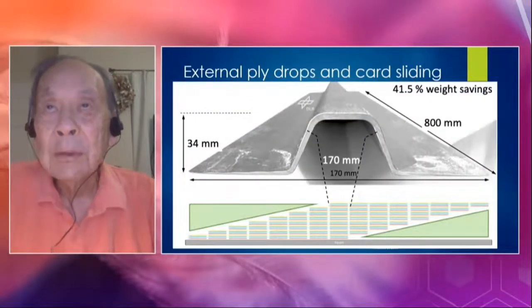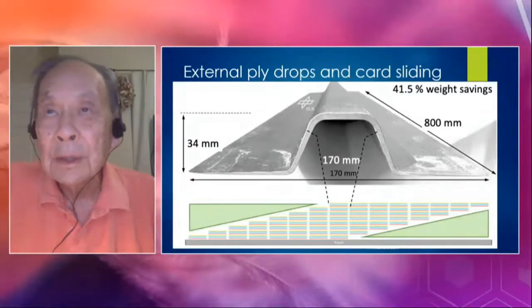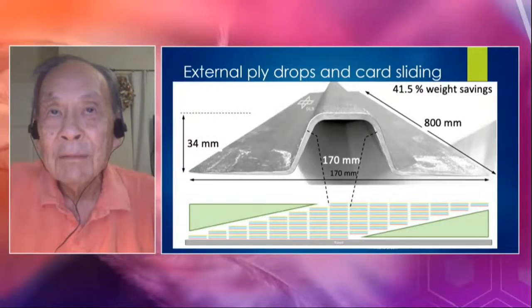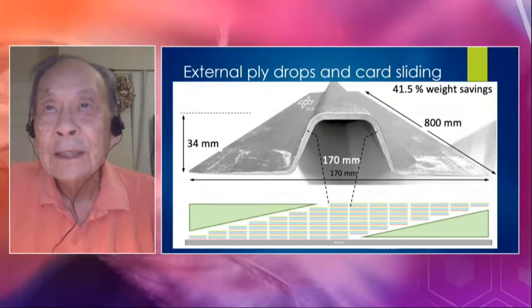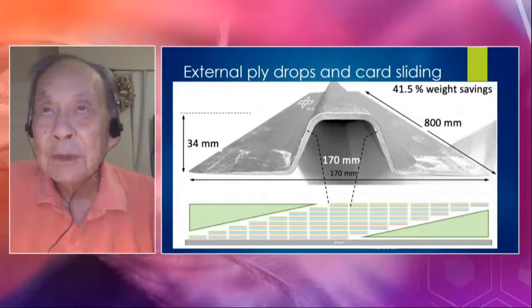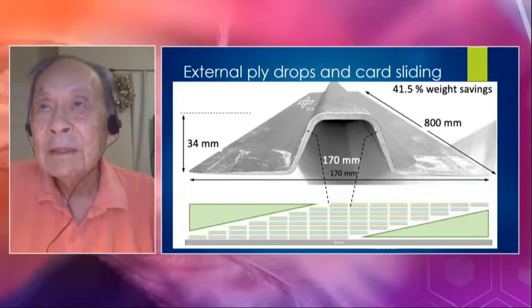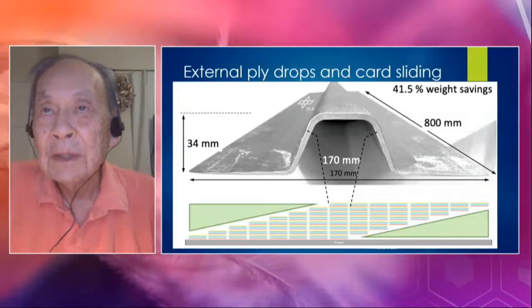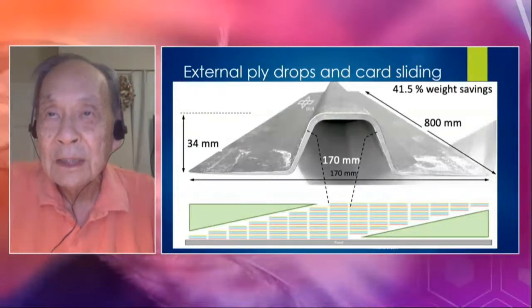Here is an example of how you can do a stringer, and this is reported in the book in chapter 3. And then you can see you can taper it from the toes, where you have the minimum number of plies, 4 plies, up to the thickest section where you need it, which is 8 plies. So it's very easy to do. In particular, this is done by card sliding.